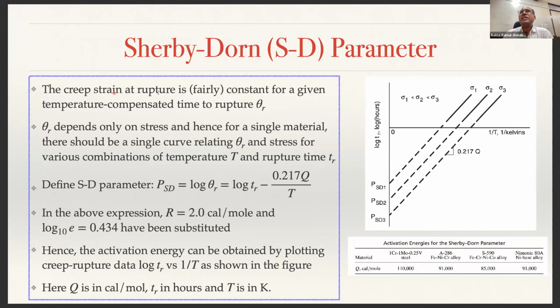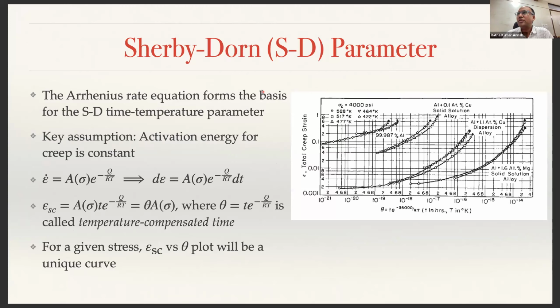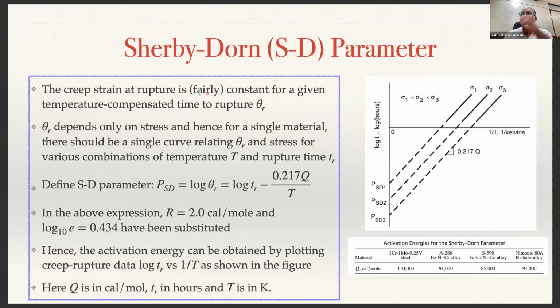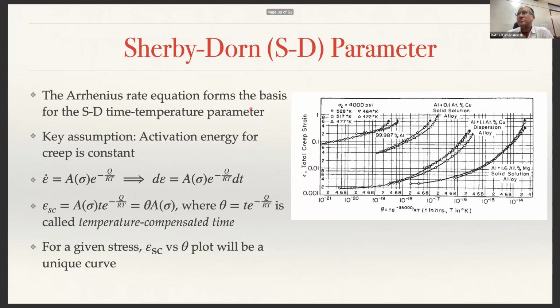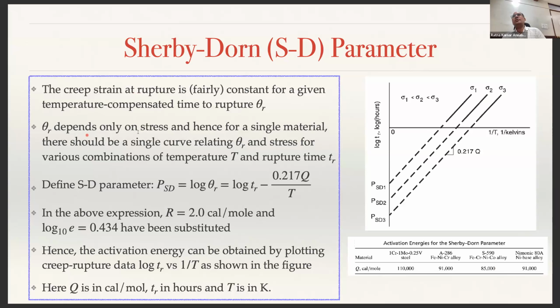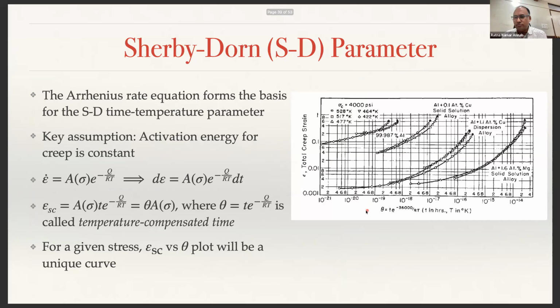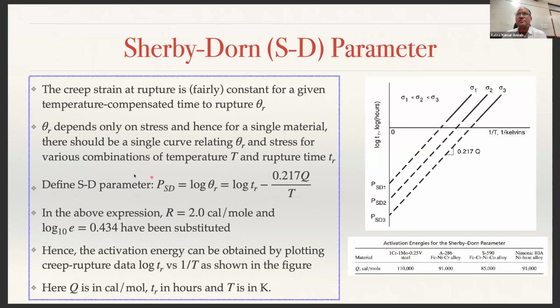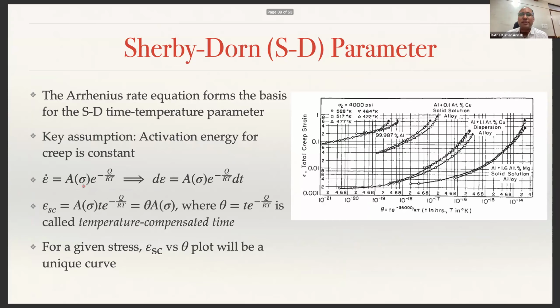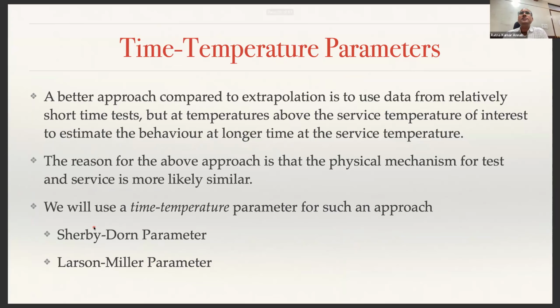And you can calculate the creep strain at rupture. The creep strain corresponding to rupture will be more or less constant for a given material, at time theta r. That is this one. So the theta r now depends only on stress. So for a single material, you should have a single curve relating theta r and stress. So you now define something called the SD parameter. What is SD? Sherby-Dorn parameter.